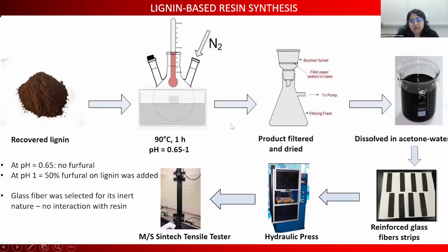Once the synthesis was complete, the product was then filtered and dried. And then initial testing was performed using glass fiber strips. So the resin was dissolved in acetone water, and inert glass fiber strips were immersed in this solution of acetone water resin, and then hydraulically cured under high pressure and temperature, and then tested under tensile load. This was to screen our initial candidates to see if we were able to produce mechanical properties that were comparable to the commercial phenol formaldehyde resin. Glass fiber strips were particularly chosen because they are inert, and it was expected there would be no interaction between the glass fibers and the resin. So the strength that we would observe from here is that of the resin alone.